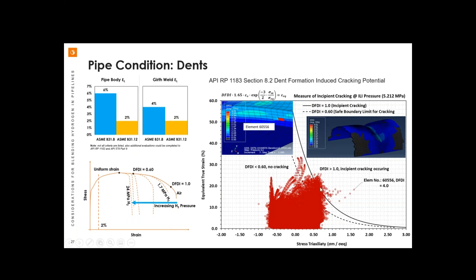So each one of these little red dots here is a little element from an FEA model. So in this graph, we actually take a pipe, we indent it and deform it, and we track the true strains. And it's only strains that combine in a certain way that lead to cracking. And so when you are above this line here, which is 1, a crack is formed, but we also apply a safety factor on top of that, 0.6. What we might see in the future is there might be a case for introducing an additional partial safety factor for hydrogen service at low blend rates. That remains to be seen though. For now, it would be very prudent to simply just follow the limits from B31.12.